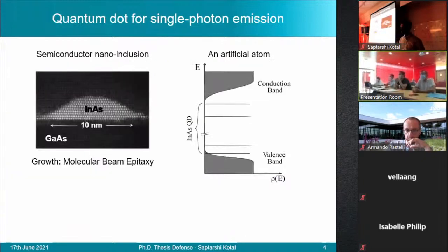Now, the component that emits photons in our sources is the quantum dot. A quantum dot is a semiconductor nano inclusion, which is surrounded by a semiconductor of a different band gap. In particular, we use indium arsenide quantum dots, as we see here, which is of the order of 10 nanometers in diameter, and it's surrounded by gallium arsenide, and the entire system is grown by molecular beam epitaxy. Now, the contrast in band gap between indium arsenide and gallium arsenide results in a strong confinement of charges within the quantum dot, thereby leading to discrete energy levels.